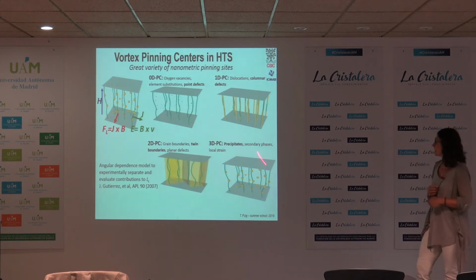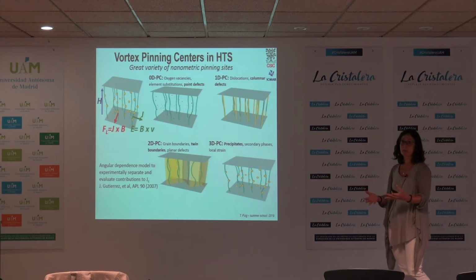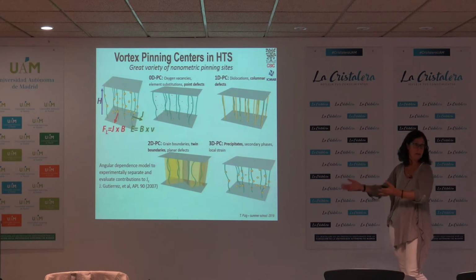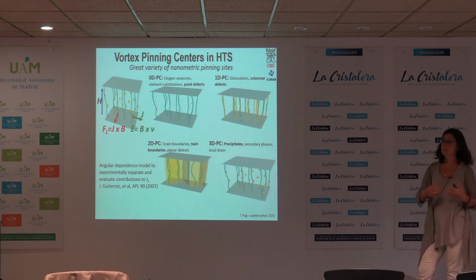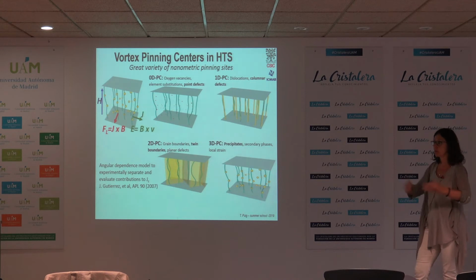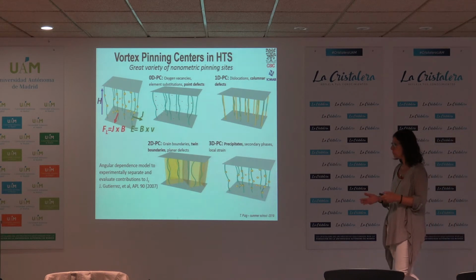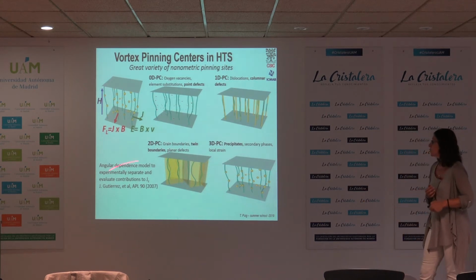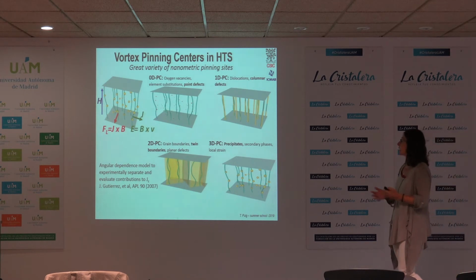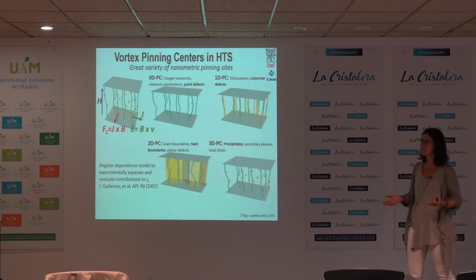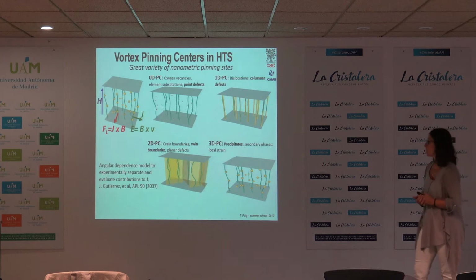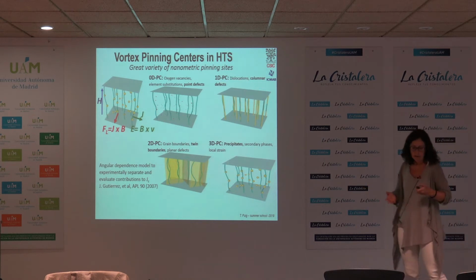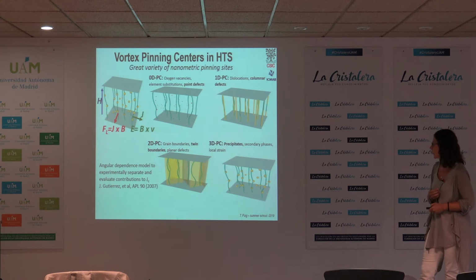But altogether, the difficulty is that at the end, when you produce a material, you have all of them there, and you have to know which of them is the one you want to promote, depending on which magnetic field and which temperature you want to work with. And for that, you need models which are able to separate these different contributions when you do a measurement. And in this we have also been contributing quite a lot.